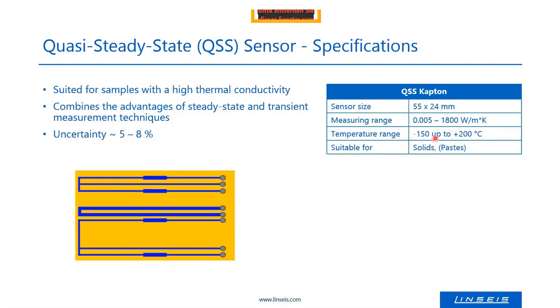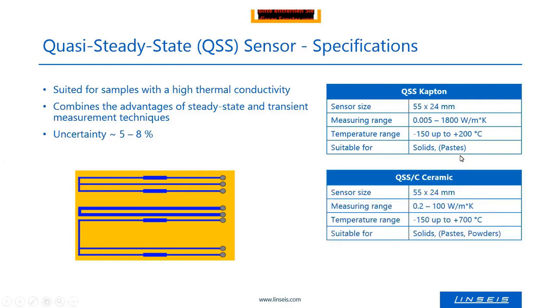The temperature range is the same compared to the THB sensors. It's suitable for solids. It could be applied also for pastes and liquids, but it makes no sense because the THB sensors are better for pastes, liquids and powders. The ceramic one is limited with respect to the measuring range. The ceramic QSS sensor, which can measure up to 700 degrees Celsius, can measure up to 100 watt per meter Kelvin.